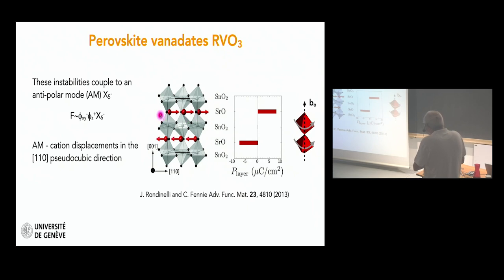You see that in the orthorhombic phase, you have this plane of strontium cations which move in this direction, but in the next unit cell, they move in the other direction. So an antipolar motion, and you can calculate, and this is what you see here, the polarization induced by this antipolar motion, and you see that it goes from plus maybe 8 microcoulomb per square centimeter to minus 8 microcoulomb per square centimeter. No net polarization because it's antipolar.